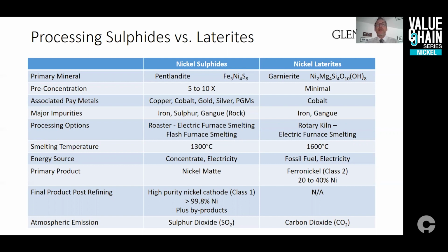The iron is desired by the customer since it's required in stainless steel production, thereby displacing alternate purchase sources of iron. In addition, iron contained in ferronickel has low impurities, unlike scrap steel. However, the customer generally doesn't pay for the iron units in ferronickel, and the producer typically pays for transportation to the customer. Furthermore, reducing the nickel content of the product increases the smelting costs. Therefore, a lower grade nickel product benefits the customer over the producer.